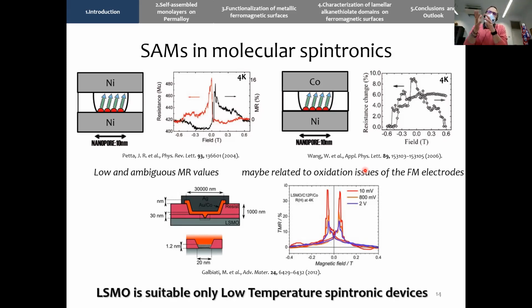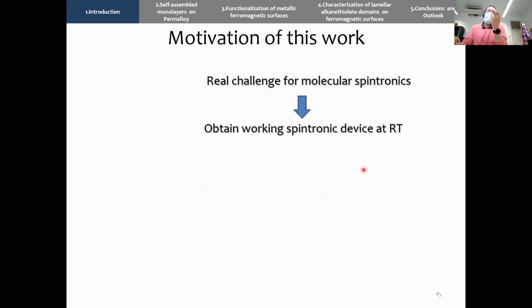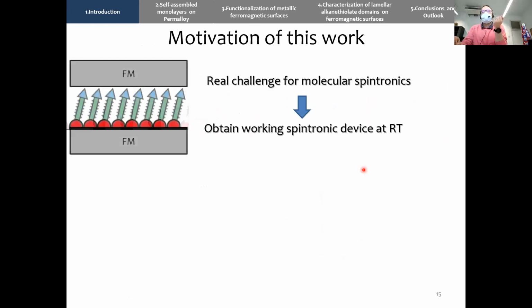So the problem with this material is that the Curie temperature of this material is well below the nitrogen boiling temperature. It's around 50 Kelvin. So we cannot reach room temperature with this kind of configuration. So the motivation of this work is that we want to obtain a working device at room temperature.